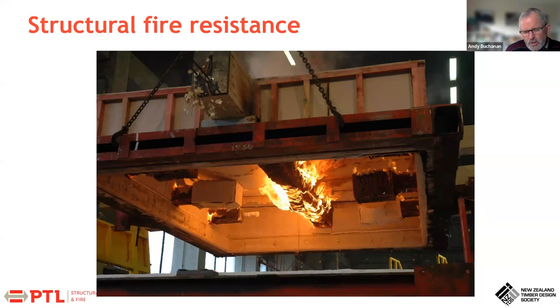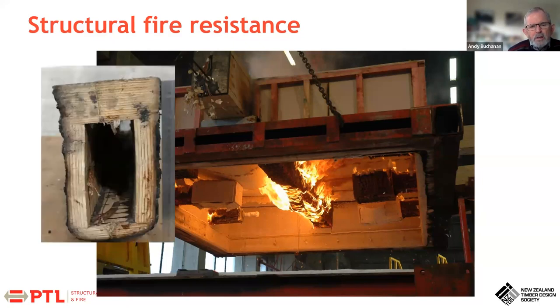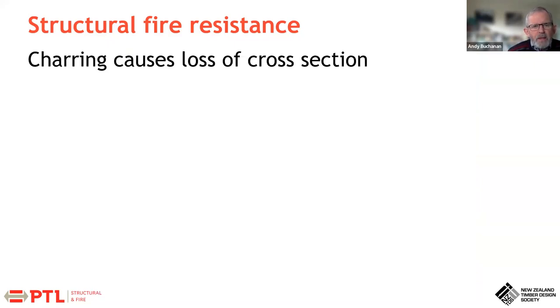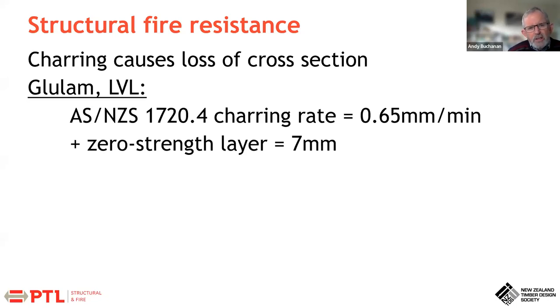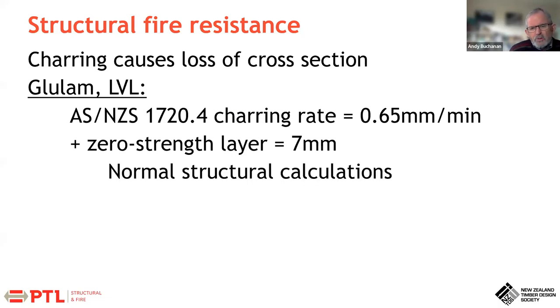I want to say something about structural fire resistance, because I know we've got structural engineers here. This is a photograph from BRANZ, a fire test of a hollow LVL box beam some years ago, which was cut open after the fire, and that's what we've got. And this is well known, that wood chars at a predictable rate, and it causes a lot of loss of the cross section. And for glue lam and LVL, we just go to this code. It used to be a chapter in NZS 3603, but it's now in the joint standard ASNZS 1720 part 4, which gives the charring rate for New Zealand grown radiata pine of 0.65 millimeters a minute, plus a zero strength layer of 7 millimeters. And after that, you can do your normal structural calculations with the reduced loads for fires.